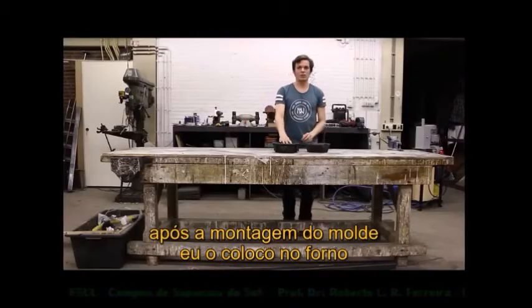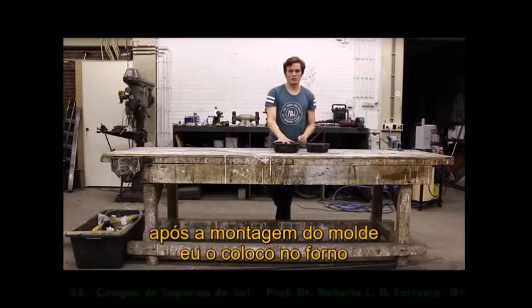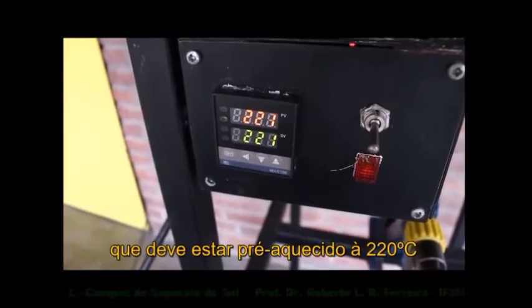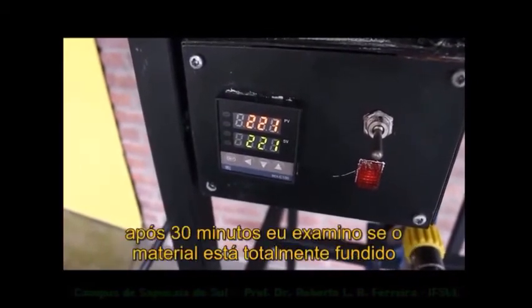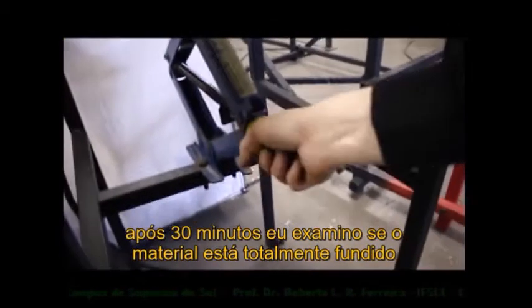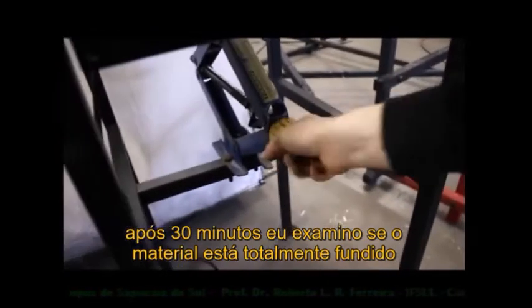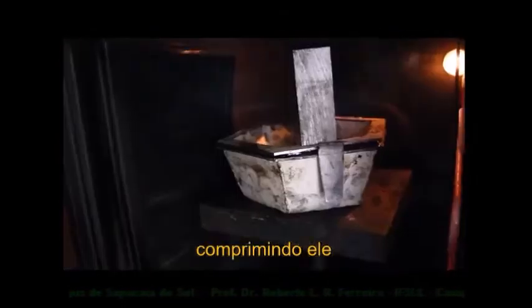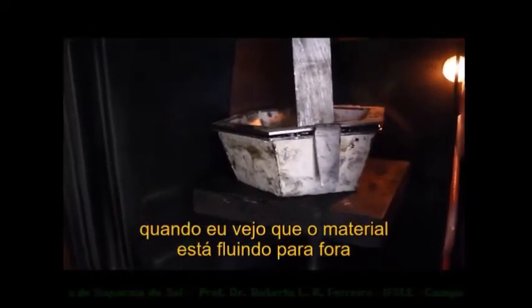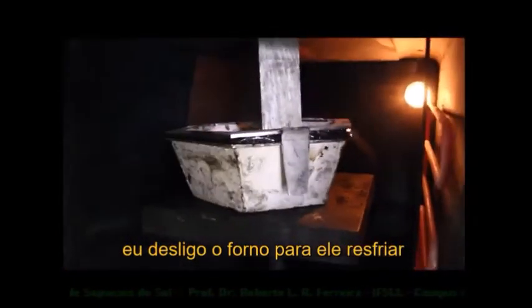After fitting the mold, I put it into the oven. The oven was preheated to 220 degrees. After 30 minutes, I checked if the material was totally molten by compressing the mold. When I saw that the material was flowing out, I turned off the oven and let it cool down.